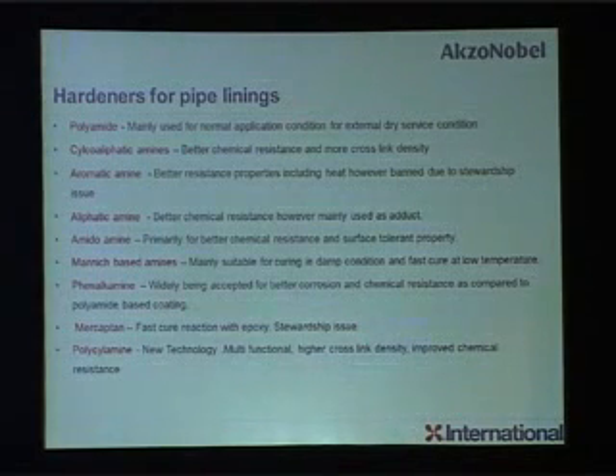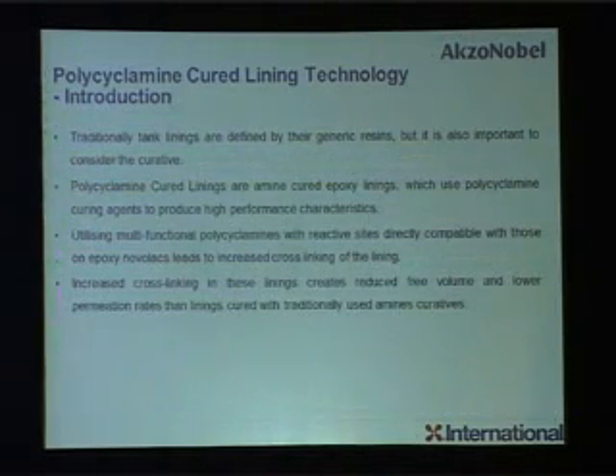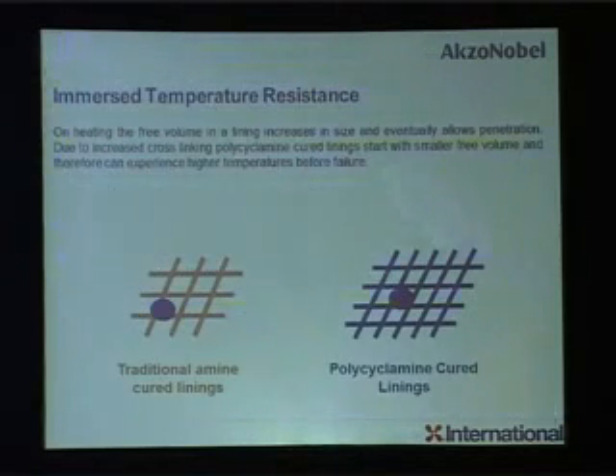But if you think about acid resistance lining, or some high temperature lining where high temperature crudes and sulfides are exposed, you need to go for a cycloaliphatic amine based epoxy novolac coating. So depending on your requirement and service temperature, you have to choose the coating. Now the recent development is polycyclamine technology. It's a patented technology from AkzoNobel. It's a special blend of amines which also has cycloaliphatic amines, and it actually enhances the functionality of the epoxies. Like we have epoxy novolac, and if we add polycyclamine, it actually multiplies the functionality and crosslink density, and it will increase the chemical resistance of the coating.